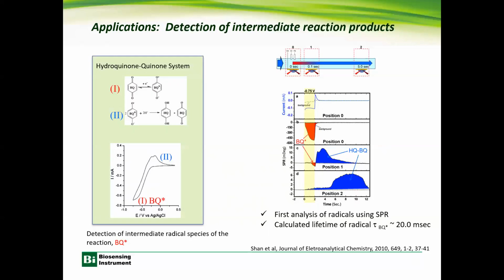So this specially designed technique combines EC with SPR, so we can measure the SPR at different stages of the time window. For example, we can produce the intermediate at one site, say position 0, and then you can measure at the different positions, like 0.1 seconds or 5 seconds after. This time between those can be controlled by the flow rate of the SPR flow system.